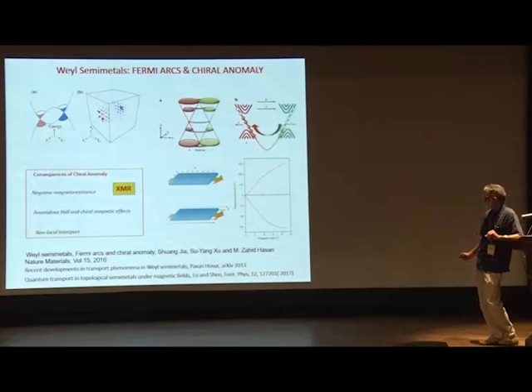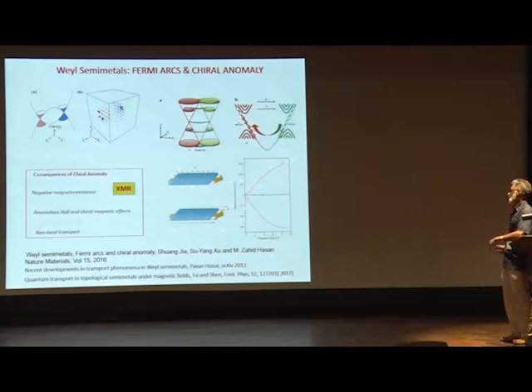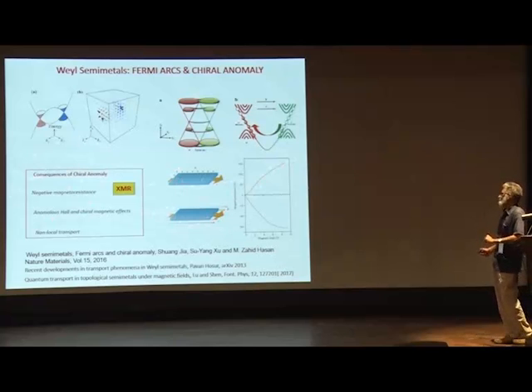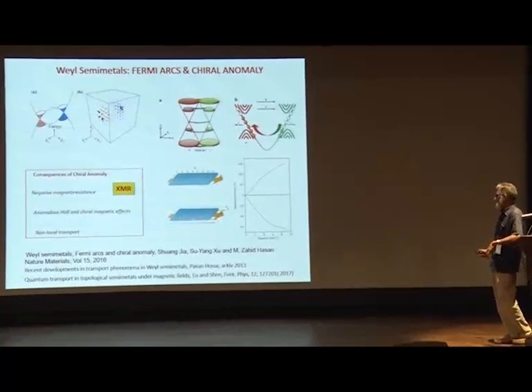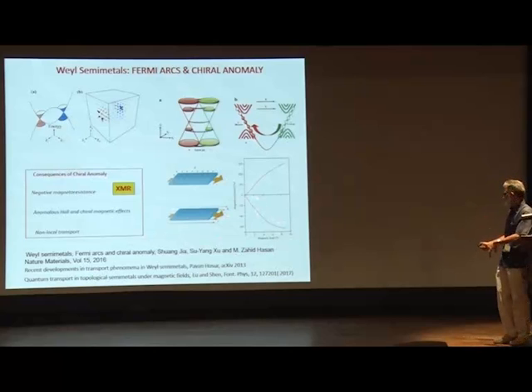One of these exotic features, well described in Pavan Hosur's article, is negative magneto resistance. Normally magneto resistance increases with magnetic field, but in Weyl semi-metals — due to chiral features — theory predicts, and experiment has confirmed, a negative magneto resistance when the electric and magnetic fields are parallel. This longitudinal magneto resistance is negative and parabolic.